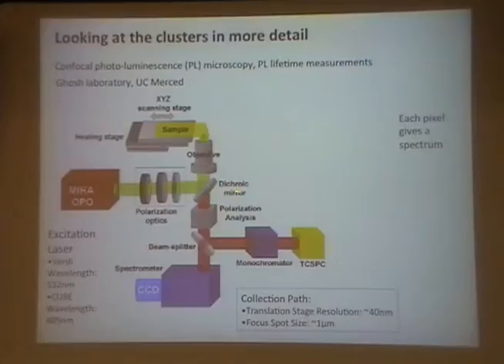We can take a quick look at this. You see we've got the illuminating laser onto the sample. We scan with X, Y, and Z. Take an image. At each point in the image, we can take the spectrum and we can analyze with a lifetime measurement. There are two spectrometers connected here, one for the image and this one for the lifetime measurement. Come back to this later on as well. The focal spot size on the sample is about 1 micron, just limited by the focus of the objective. And we can scan with the nano scanning stage, so we can scan around the sample quite easily.